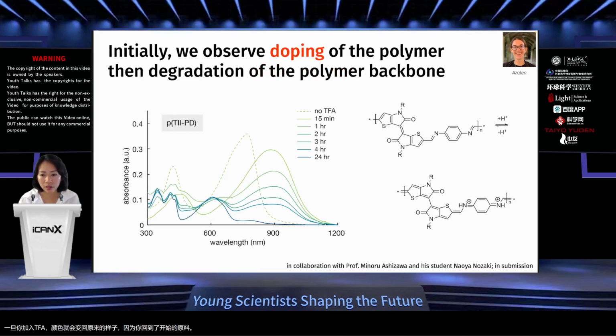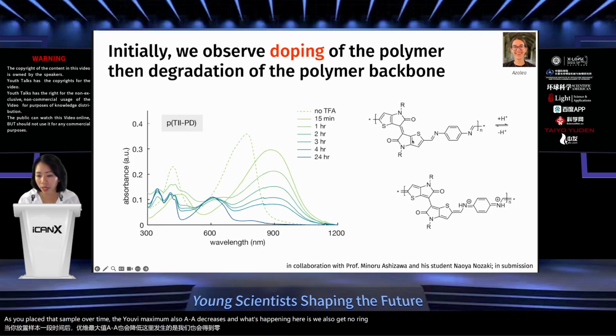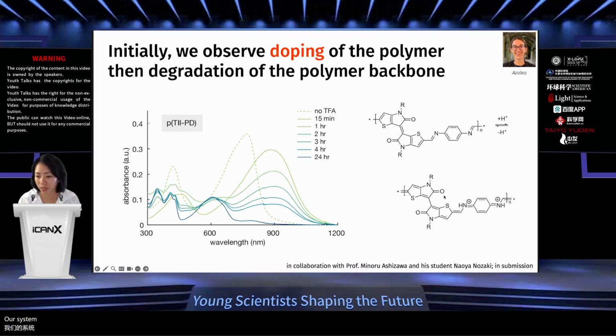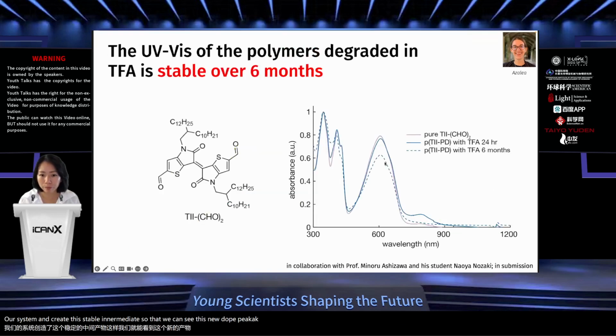And if you add TFA again, we actually see a really nice shift in the doping immediately in the maximum of the UV vis. As you place that sample over time, the UV vis maximum also decreases. And what's happening here is we also get no ring opening, and that allows us to dope our system and create this stable intermediate so that we can see this new dope peak.